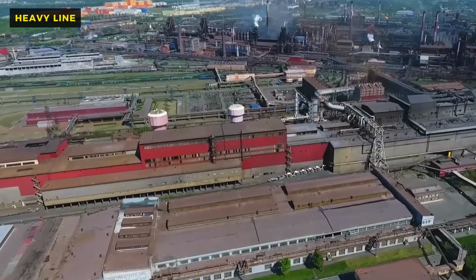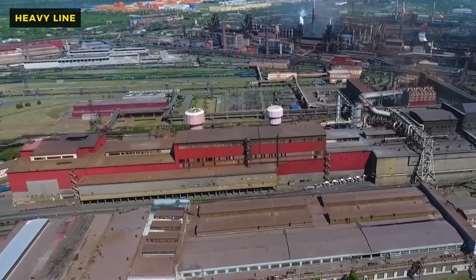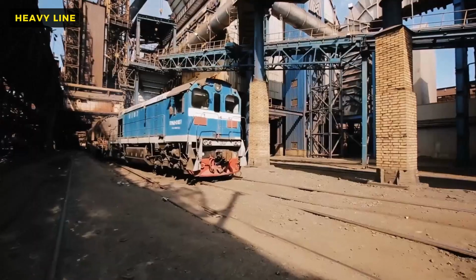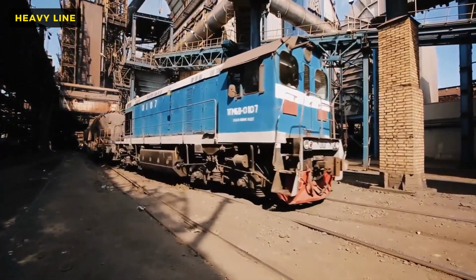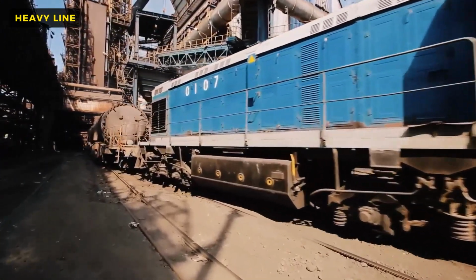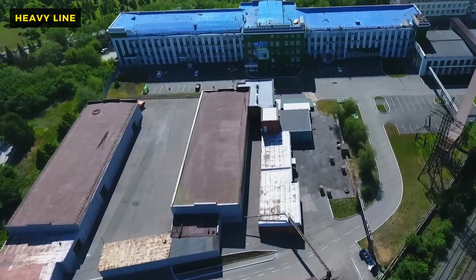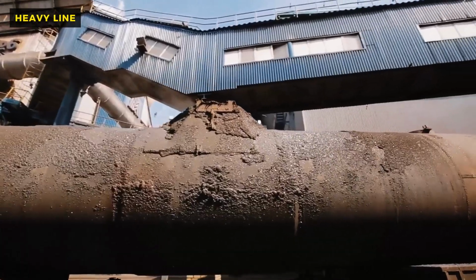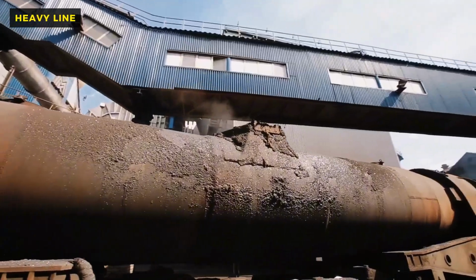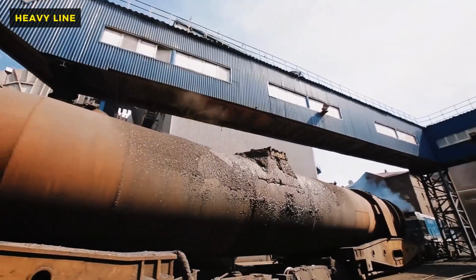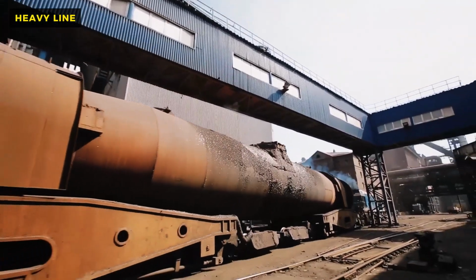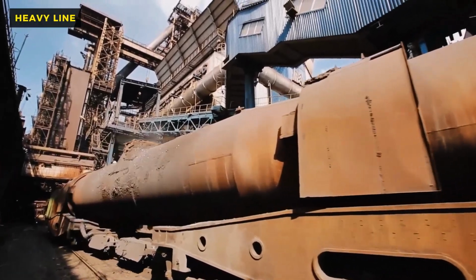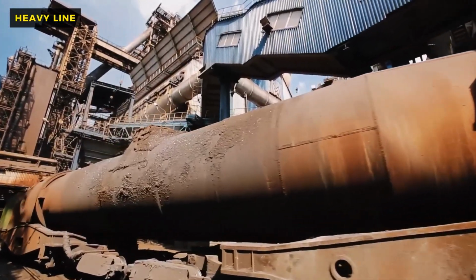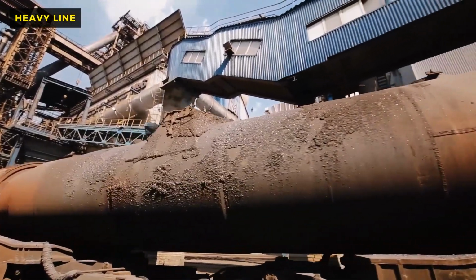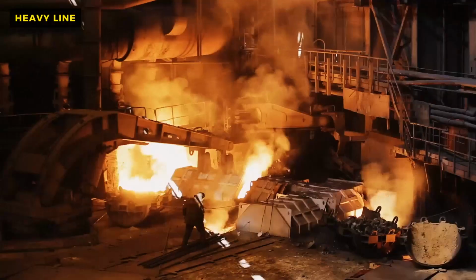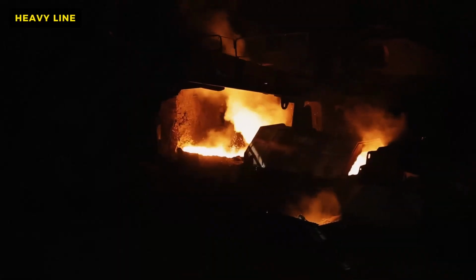By the time the ore reaches the bottom, it has been stripped of its oxygen and melted into liquid iron. The remaining rock and impurities float on top of the iron as slag. It is a continuous, roaring process, a controlled explosion that never ends. The pressure inside is immense, several atmospheres of hot gas pushing outward against the steel shell, which is lined with refractory bricks and cooled by thousands of liters of water circulating through copper staves embedded in the walls.